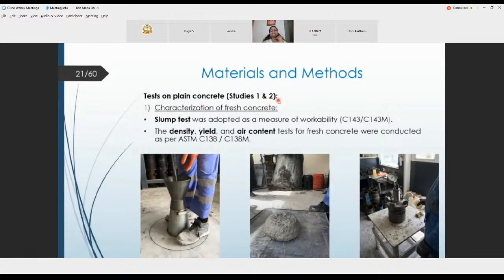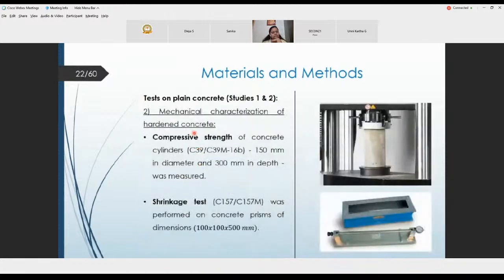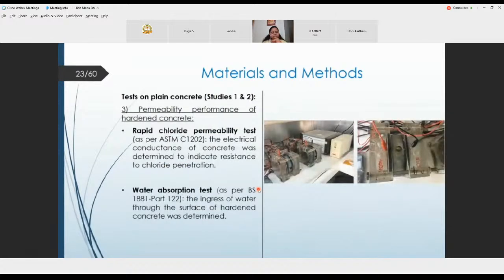For studies 1 and 2, we conducted tests on plain concrete - these are the typical slump test, density, yield, air content according to ASTM standards. We also conducted mechanical characterization tests, typically the compressive test and shrinkage test, as shown here.